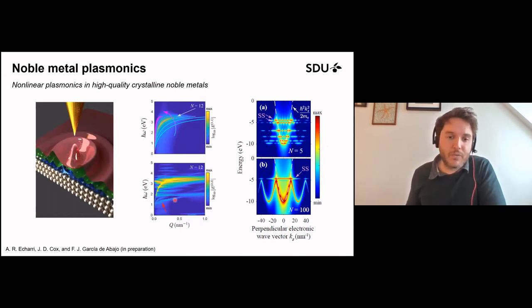Also in parallel with my former group at ICFO, we have a collaboration to explore these crystalline noble metal thin films in the context of nonlinear plasmonics. So if they're higher quality plasmonic materials, and also if they're incredibly thin, they have more surface to volume ratio, they should offer a more intense nonlinear optical response. So we're using atomistic theory that we've developed to describe the nonlinear optical phenomena in these systems. And you can think of things again like harmonic generation, but happening on the nanoscale, actually excited by a localized source, like a metal tip that can launch plasmons, and they can be upconverted through nonlinear optical processes.